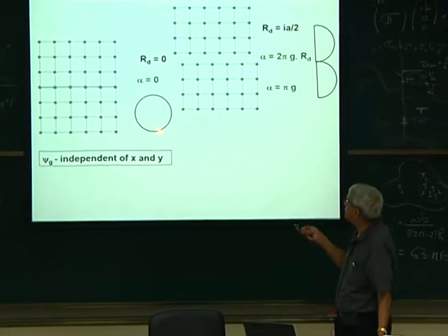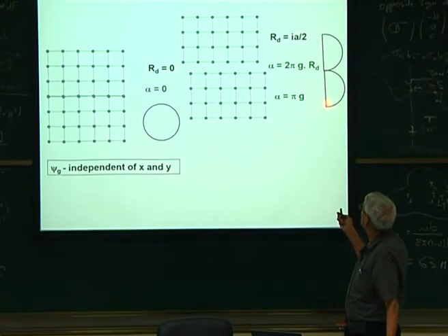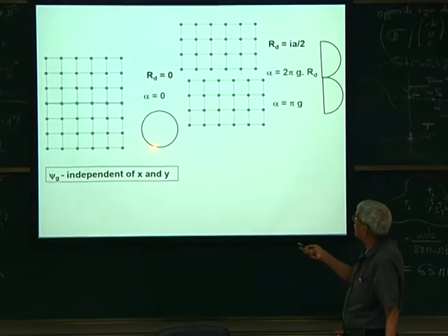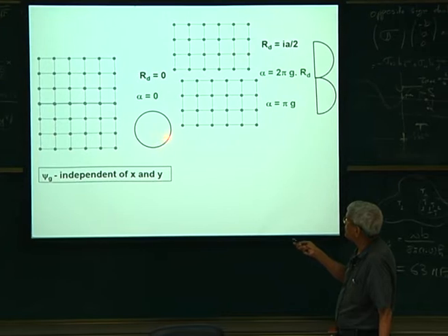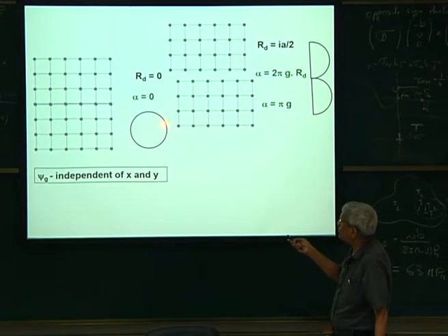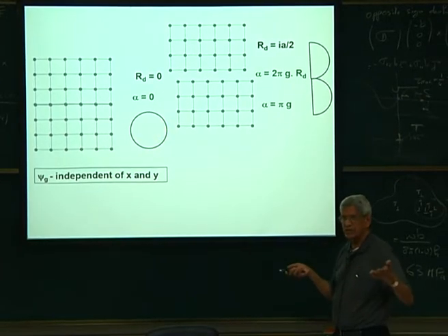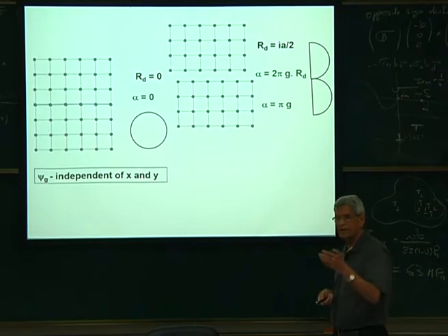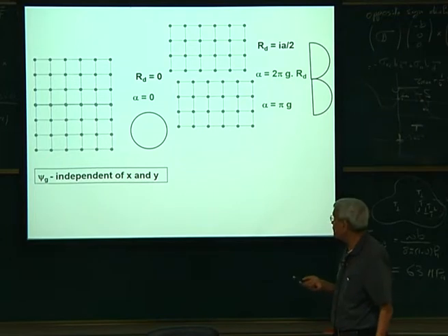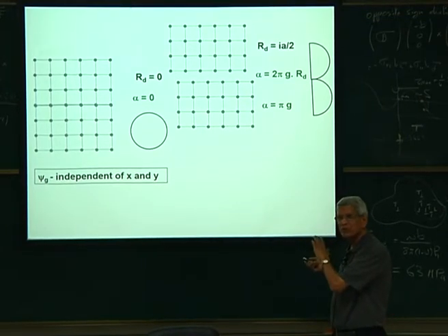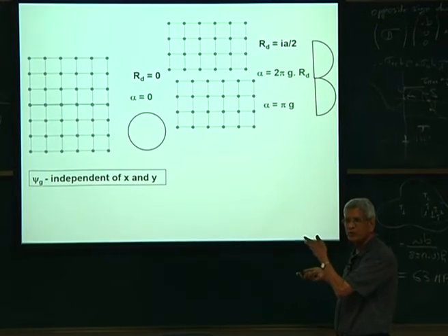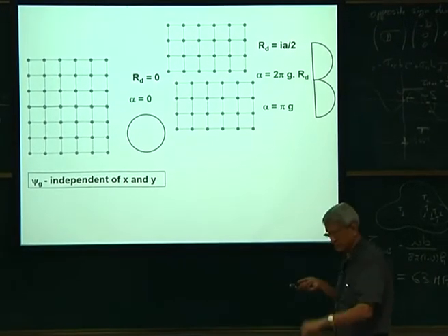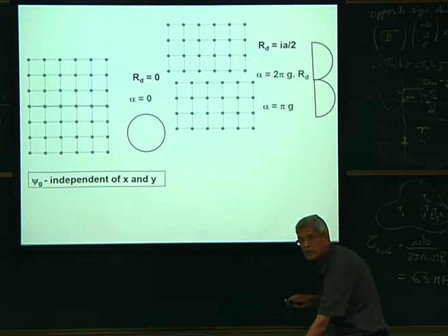If a defect is being introduced into it, what does this say from here? If I plot from here to here, it is like many waves, each making a small angle. The net amplitude and the angle at which the phase of this wave function occurs is the information we get from this. This could also be used to find the amplitude, and from the amplitude, taking I star, we get the intensity. This is what the calculation is about.